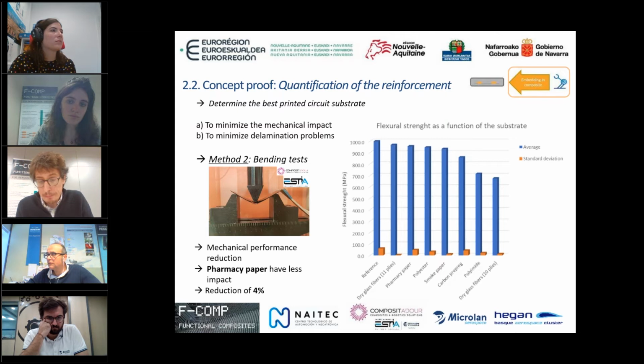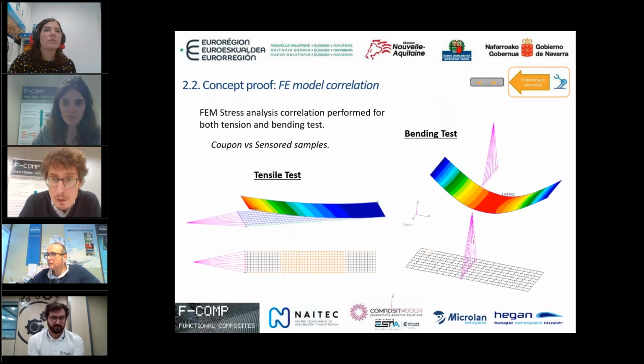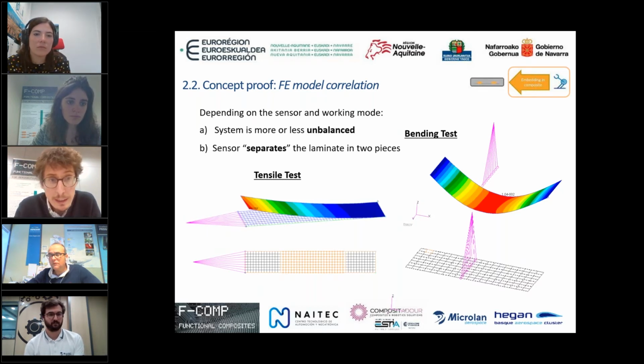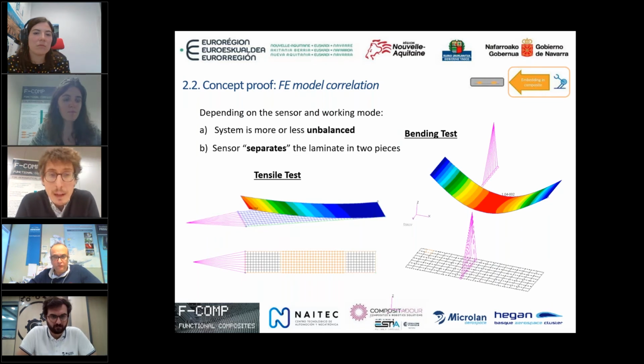between the different plies. For verifying these findings, we built some finite element models to see if what we were seeing was caused by the material, by the test itself, or whatever. We verify with this comparison between the coupon and the sensor examples that, when we put a sensor in a certain position of the composite, in this case almost in the most outer position of the layup, we started with a symmetric and balanced solution. When we put the sensor, the final stack up is unbalanced. This makes that even with a simple tensile force, you see a deformation. So we already need somehow to balance this.